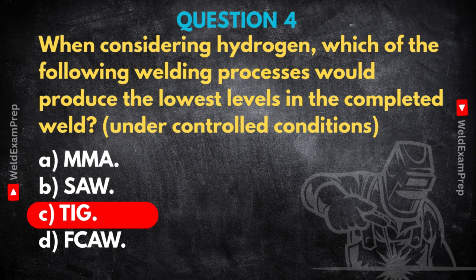And why is minimizing hydrogen so vital? We mentioned it's a headache, but what's the real danger? The big danger is hydrogen-induced cracking, also called cold cracking or delayed cracking. Hydrogen is sneaky. It diffuses into the steel, especially the HAZ, and can cause tiny cracks to form, sometimes hours or days after welding. Days later.